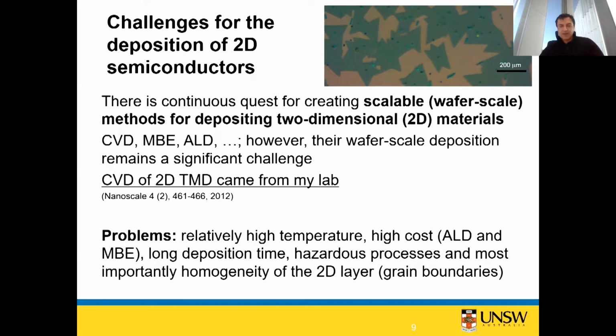And also, for instance, molybdenum disulfide or tungsten disulfide and many other dichalcogenides, when they grow into triangular forms, because nucleation happens at different locations on the substrate, they eventually reach each other, grow on top of each other, or become stitched. They make these very bad boundaries that cause scattering of electrons and holes. As an electronic material, this is absolutely non-ideal. We can use methods like ALD, molecular beam epitaxy as well, which is very expensive, of course. They are very expensive, they're limiting everything.